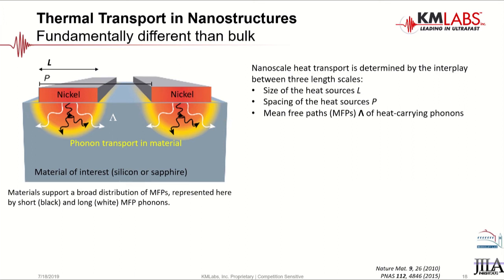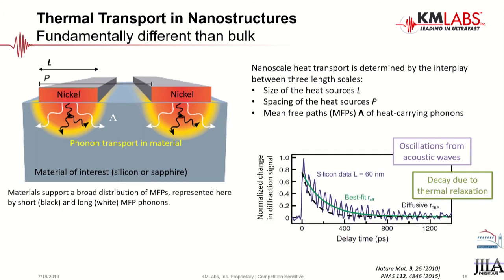And it turns out that phonon transport effect is really dictated by a few different length scales, and that is the size of the heat sources, the spacing in between them, and then some characteristic mean-free paths of the phonons themselves. And so we can do this kind of pump probe scheme where we're pumping in energy, and then we're doing a probe measurement that's essentially measuring the vibrational position of those nickel wires. And we can watch that vibration essentially ring down and make its way back to equilibrium. And the rate at which that's decaying, which is what's shown by the green line here, is essentially representing the rate of thermal diffusion effects of those phonons moving away from the nickel.